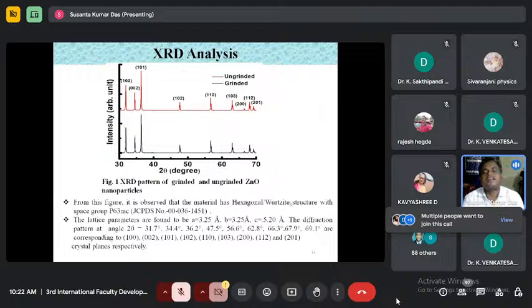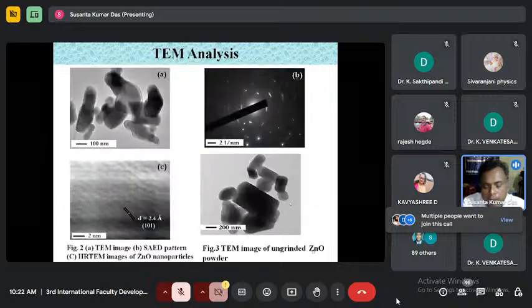Now the XRD analysis. In the subsequent things, I'll mostly deal with the results. The important results I'll discuss, and many things are similar, so I'll try to skip them. So you see, we had gone for XRD and we found that there is almost no peak change. But we have done the Scherrer analysis and we found that the crystalline size was much reduced, and that was also verified through TEM.